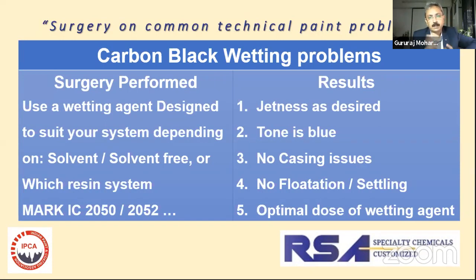The result when you use a highly specialized product for your carbon blacks is you get the desired jetness, the tone is blue, there are no issues like casing, flotation, settling, and the dose is very optimized. It's the best dose that you can use if you are using a specialized product.